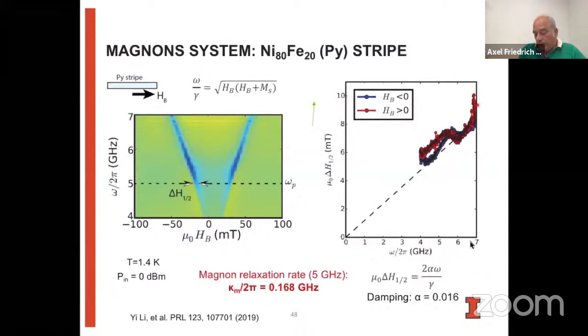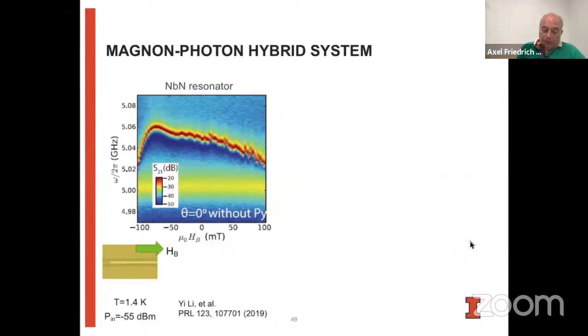And so we do extract this damping here from the dependence of the line width as a function of frequency. And while there is some additional structure in there, it's mostly linear. So now we look at the magnon-photon hybrid system. As a reminder, this is the field dependence of the resonance frequency of the niobium nitride resonator without the permalloy.